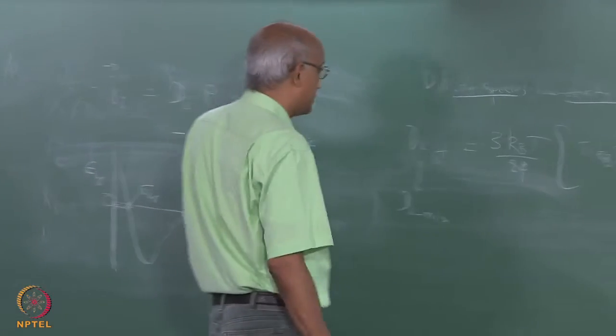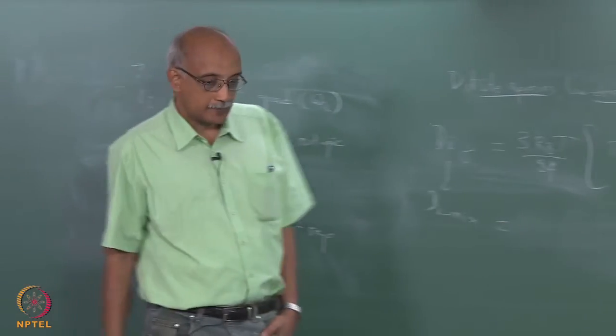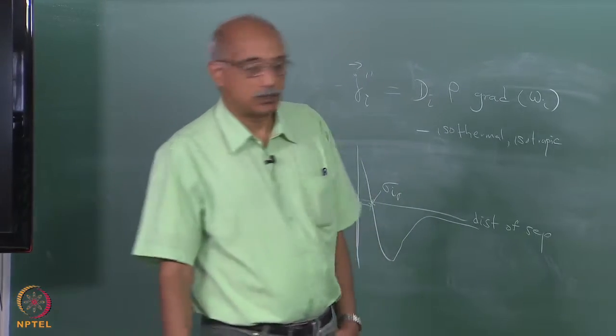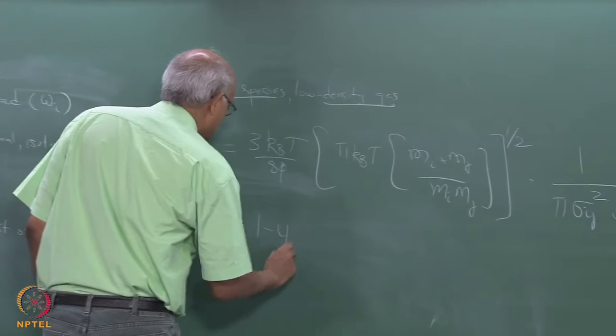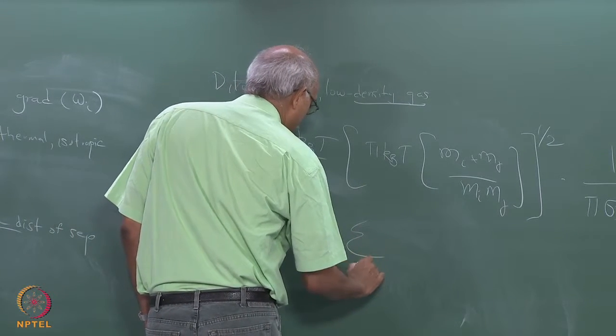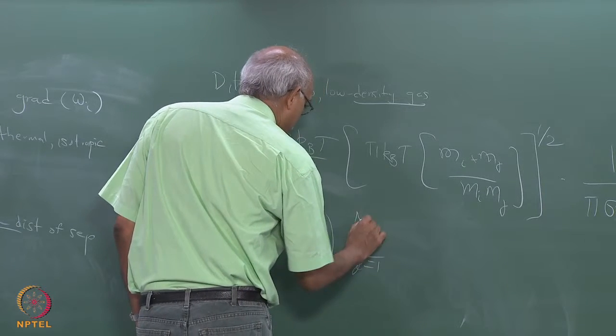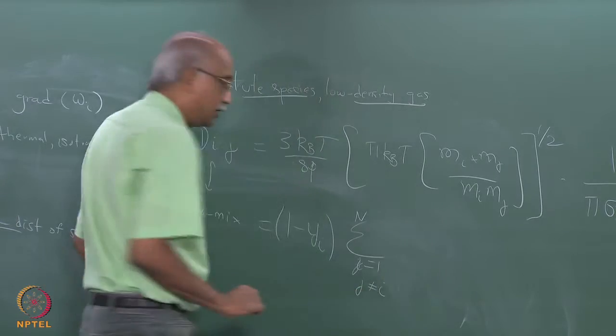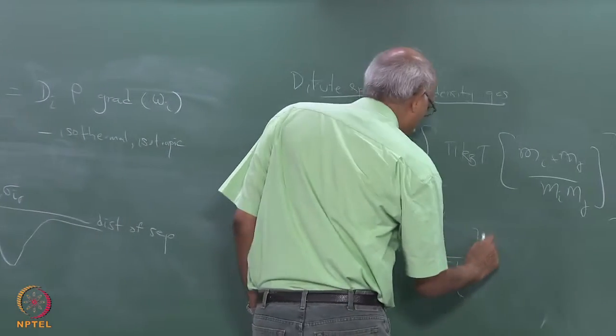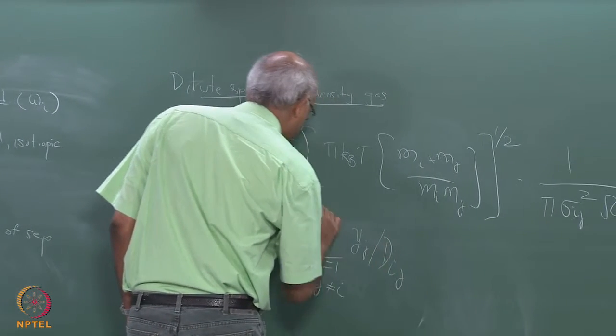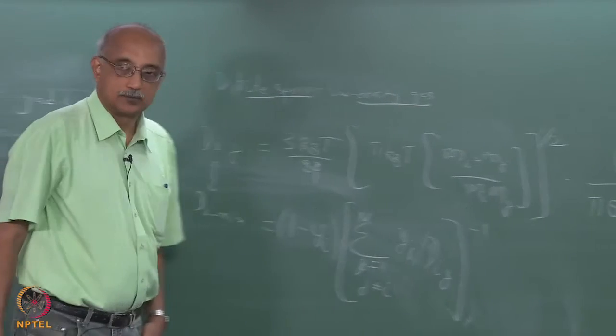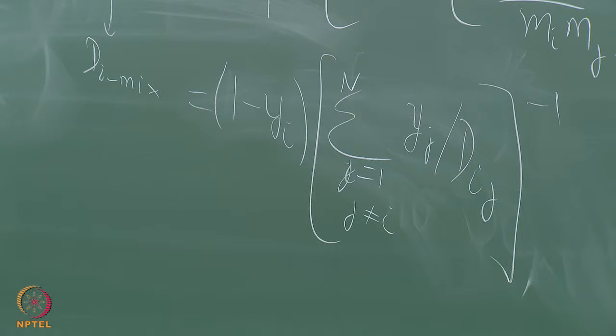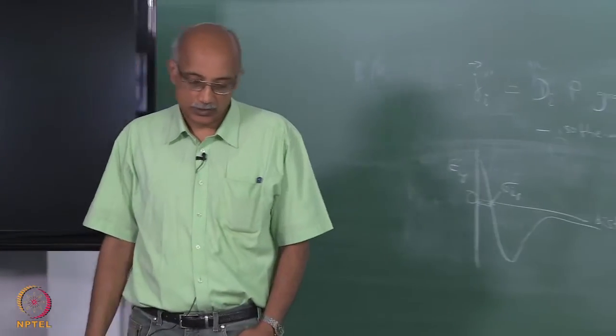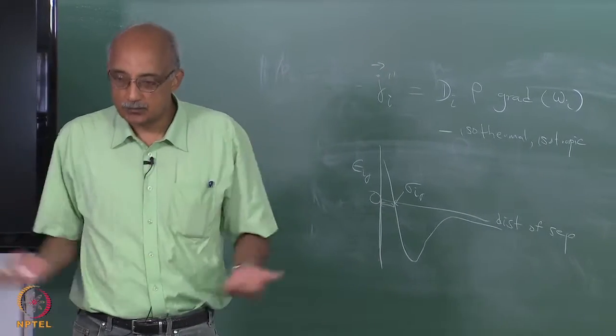So, once you have estimated this parameter, the binary diffusion coefficient, the diffusivity of species i in the mixture of species can be derived as 1 minus yi times summation of j equal to 1 to n, where j is not equal to i, of yj over dij, the whole thing to the power minus 1. So, it is essentially estimated as a weighted sum of the binary diffusion coefficients, which enables us to calculate the prevailing diffusion coefficient in the case where the collisions are not only binary, but multi-species are involved.